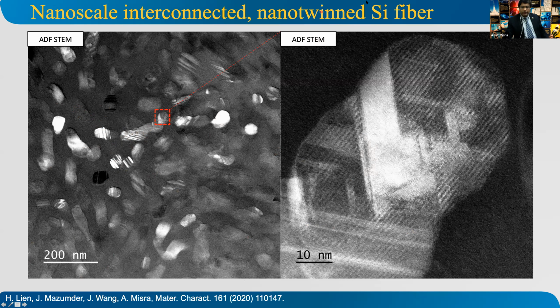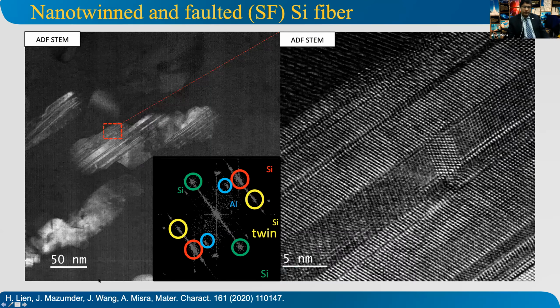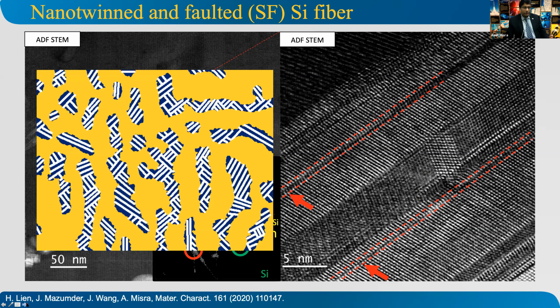twins. So inside the silicon fiber, as it is growing from a liquid phase in the eutectic, the silicon fibers are not defect free. They're actually growing in this twin structure. So this is a silicon fiber. Inside you see these planar contrast from these planar defects that are full of these stacking faults and twins. So we have created a nano-twinned and faulted silicon fiber inside the eutectic matrix, inside that laser zone, creating a hierarchy of defects in that very simple composition.